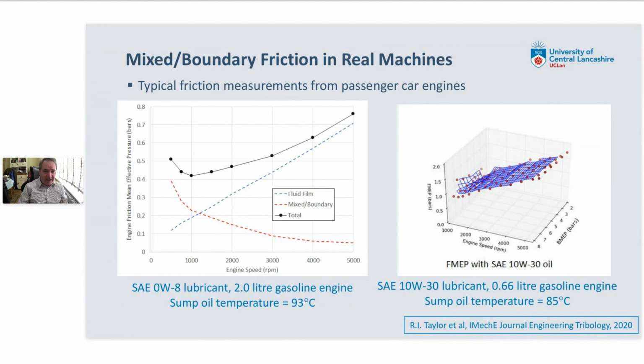We also tested a different engine, which was a 3-cylinder 0.66 litre engine. This is the type of engine used in these Japanese K cars, which are quite fuel efficient. In this particular case, the engine was fired, as it's normally done in a real engine. And we found that, again, the friction mean effective pressure generally goes up with engine speed, but at very low speeds we can see it go up as the speed decreases. So again, we see this effect of mixed and boundary friction being quite important at low engine speeds. This data also showed that, somewhat surprisingly, the friction in the engine wasn't massively dependent on the load of the engine. There's a slight effect, but it's not as big as you might imagine, which is one reason why motored tests are often done, because they don't usually give a substantially different friction than when you do it fired.